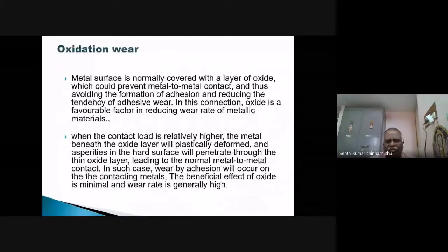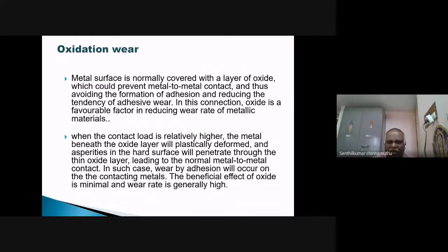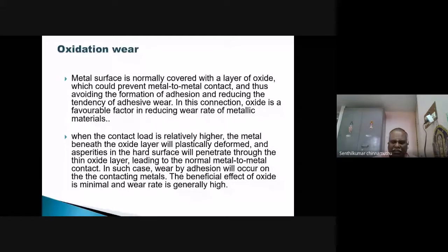Next, oxidation wear. Usually, the metal surface is normally covered by oxide layers, particularly magnesium and aluminum, which could prevent metal to metal contact, avoiding the formation of adhesion and reducing the tendency of adhesive wear. In this case, the oxide is favorable for the metal, reducing the wear in the metallic material. When the contact load or contact pressure is relatively higher, the metal beneath the oxide layer will be plastically deformed and the asperities on the hard surface will penetrate the thin oxide layer, leading to normal metal to metal contact. In such a case, wear by adhesion will occur on the contacting material. The beneficial effect of oxide is minimal and the wear rate is generally high.